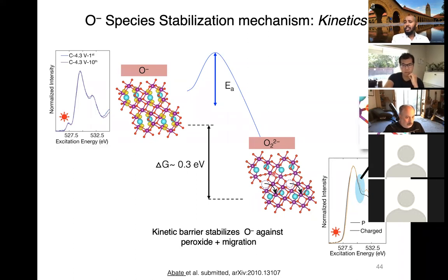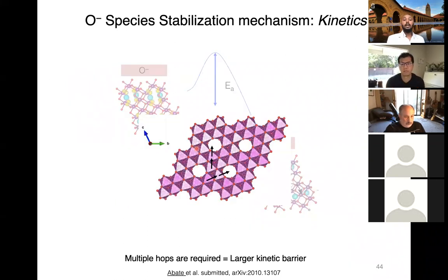And the question is why this is unique to this material. In this material, like I mentioned, there's an ordered defect. Because of the ordered defect, the number of hopping sites required for migration of a cationic disorder is higher than in previously reported systems. And therefore, one can think of this design principle where we introduce defects in a given material in an ordered fashion to improve Coulombic stabilization, thereby stabilizing the O- species through the Coulombic interaction, but also improving the kinetic barrier to form a peroxide or a dimer formation. So this will be the design principle that we like to take away and apply to other lithium and sodium systems to achieve such exceptionally low hysteresis as we observe in this material.